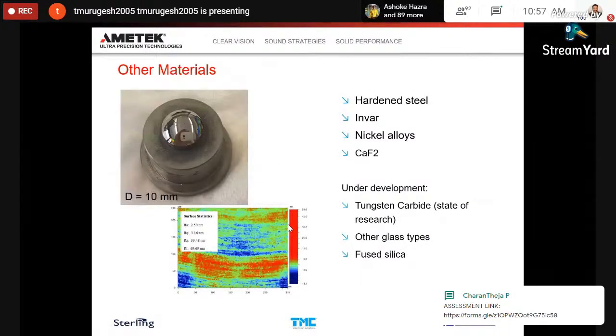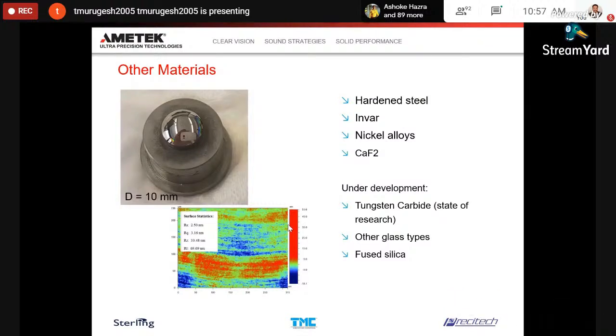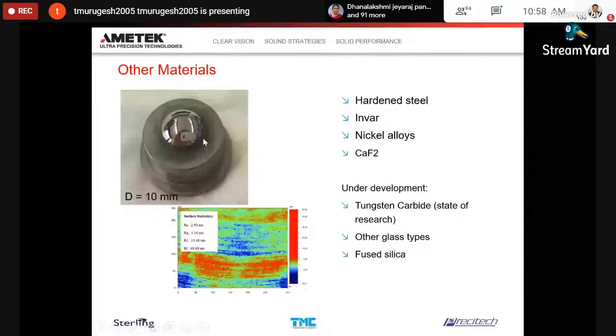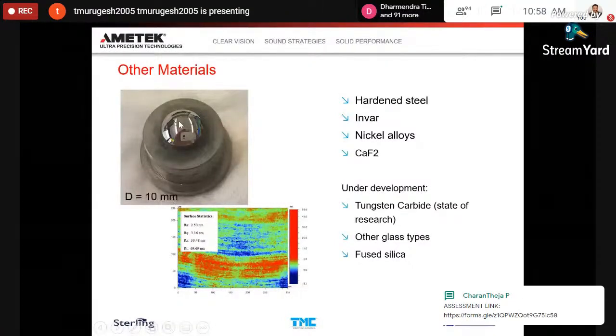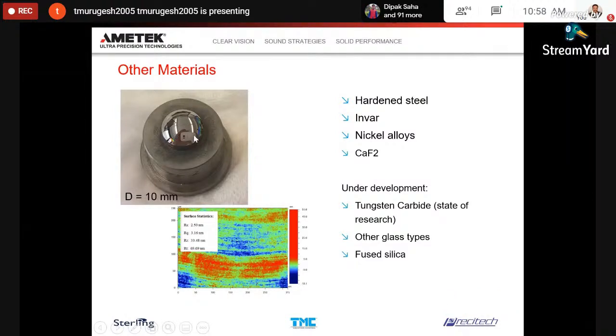What are all the other materials that are now possible? Earlier, these were impossible to do diamond turning on the machine: hardened steel, Invar, for example, nickel alloys, calcium fluoride. And we are also now able to machine ceramics like tungsten carbide. Fused silica is a material which has almost zero expansion at higher temperatures as well. These fused silica components, like gyroscopes, go onto space satellites as well. For example, this shows a tungsten carbide where the diameter is 10 millimeters. You can see we have created an optics surface on this material.